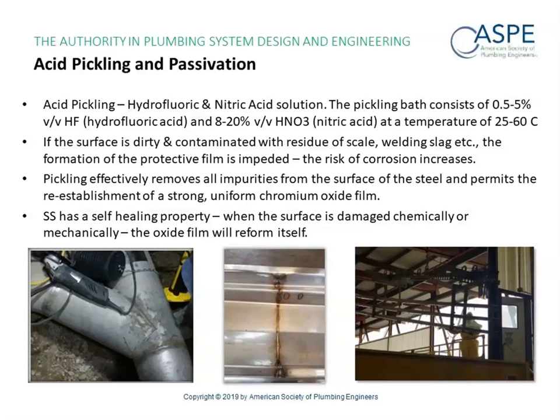So as to pickling and passivation, you take all welded corners, all welded fittings, and you submerge them in a hydrofluoric and nitric acid solution. If the surface is dirty, what it usually is, with a residue scale, welding slag, the formation of the passivation or the chromium oxide is impeded. So that increases the risk of corrosion.